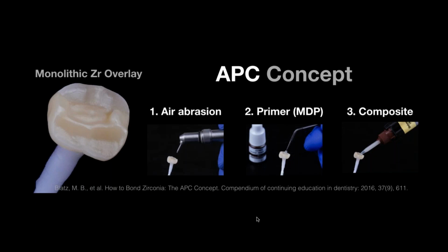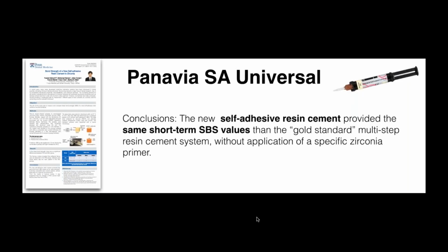And this primer needs to contain MDP. That's the phosphate monomer that bonds to the oxides, to zirconium oxide, to titanium oxide. So Panavia is the original cement that had this specific primer with MDP. Nowadays, many cement systems have it available, but this is the gold standard. And then we apply the resin cement after the application of the specific primer. Nowadays, there's a new version called Panavia SA Universal, which has the MDP inside the resin cement.